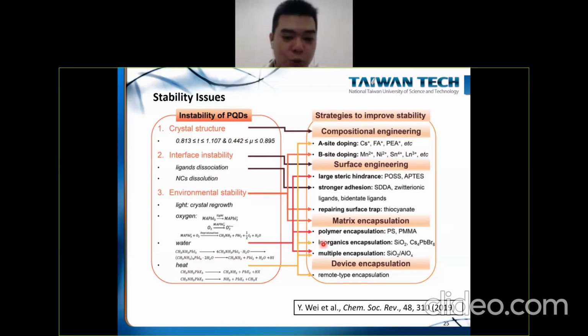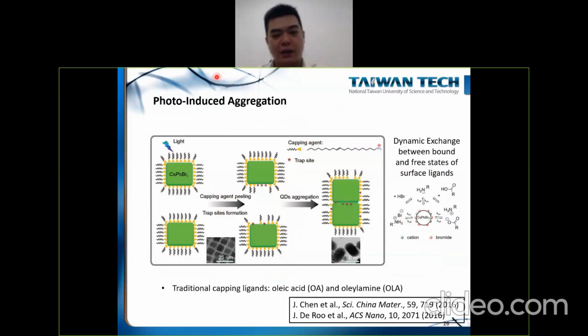But there's one problem that remains, which is the light-induced crystal regrowth problem. So what is the light-induced crystal regrowth problem? For quantum dots, we traditionally use capping ligands such as oleic acid or oleylamine for capping and preventing the quantum dots from growing bigger. However, the interaction between the traditional capping ligand and the quantum dot is not very strong. Actually it undergoes a dynamic exchange between the bound state and the free state. So if you have light excitation, some of the ligands will be peeled off, and if neighboring quantum dots have their capping ligands peeled off, they will aggregate into larger crystals, and the light emission properties will disappear.